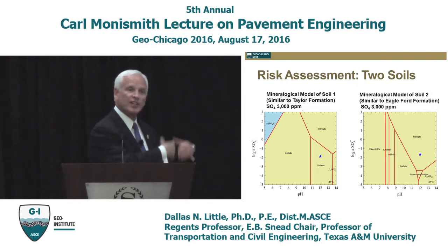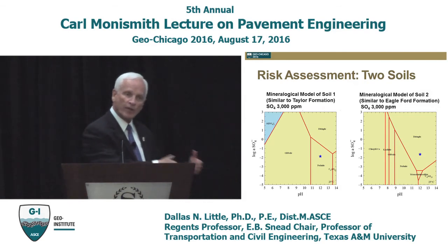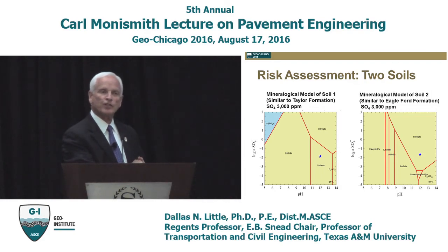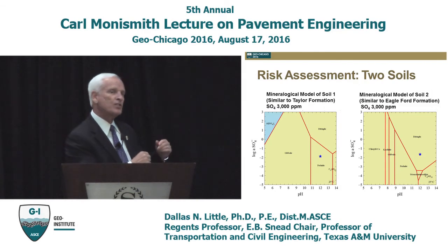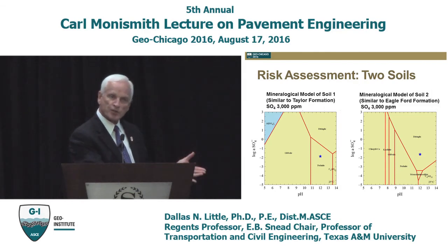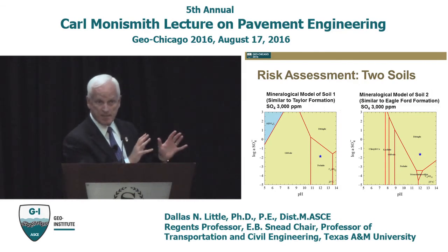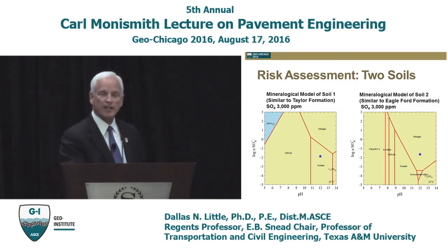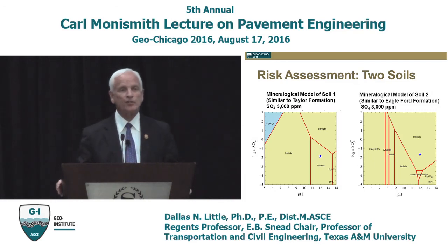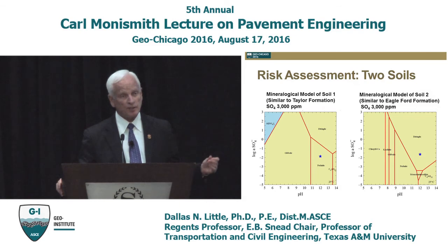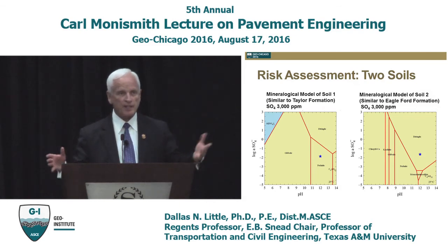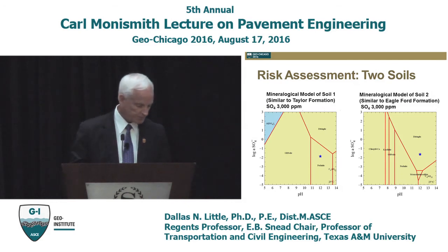Now, the other thing you can do is add things to your mineral. One thing that we found would be successful is to add soluble silica. Soluble silica means that you have the free energy to form something other than ettringite many times. And we found that adding some Class F fly ash or maybe some granulated ground blast furnace slag can often provide the silica to prevent the reaction causing ettringite to form.